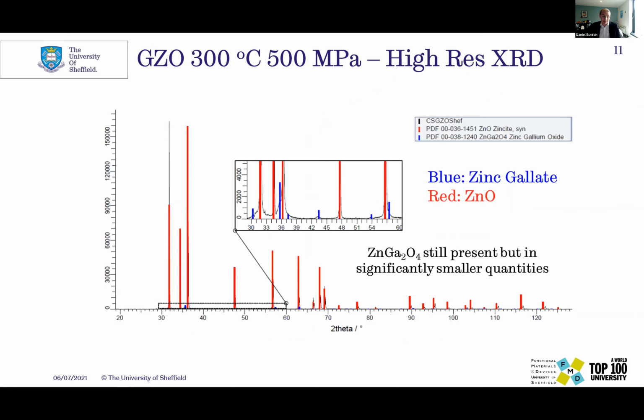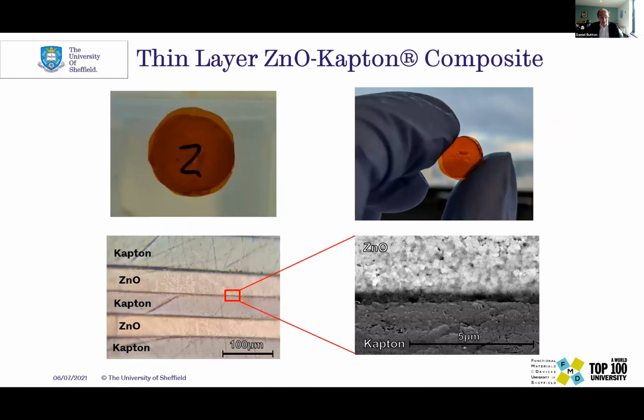Now, it is still present, but it means that with the cold sintering process, we can perhaps control it much better if we do want it, and it does reduce significantly if we don't want it. But yeah, these are significant pressures. Usually you'd have to go to something like 1200 to 1300 to actually get rid of this gallate phase. So it's a significant reduction in temperature.